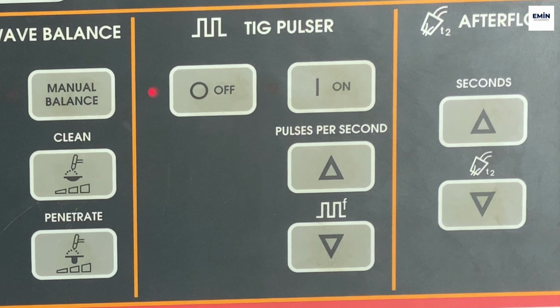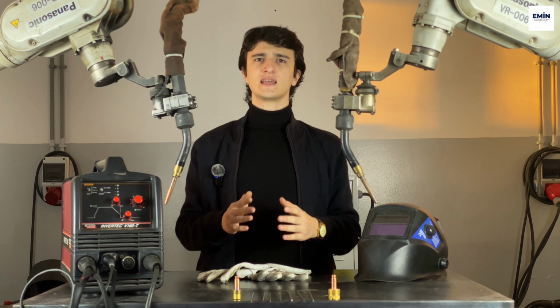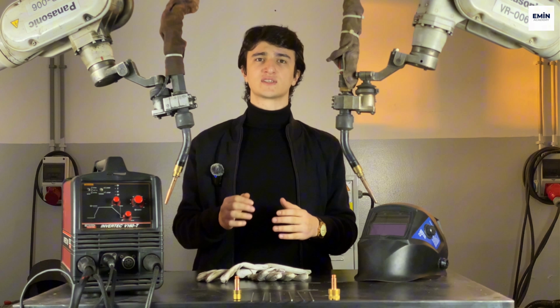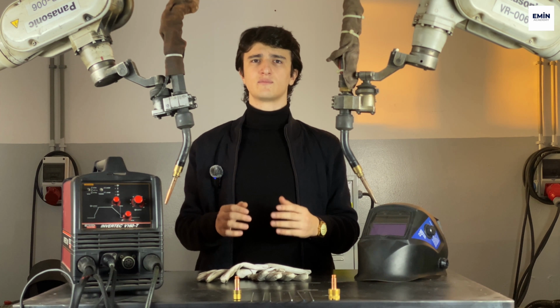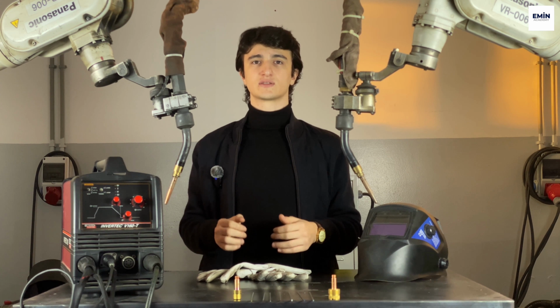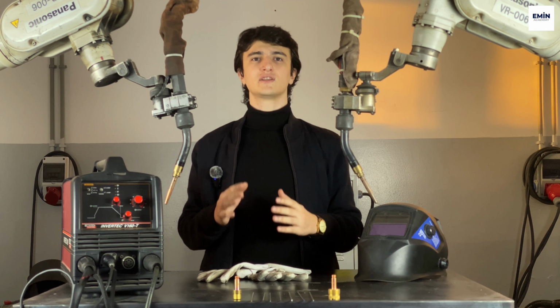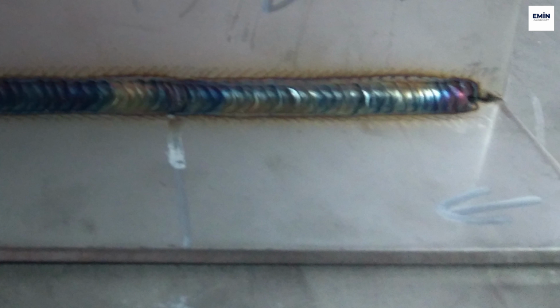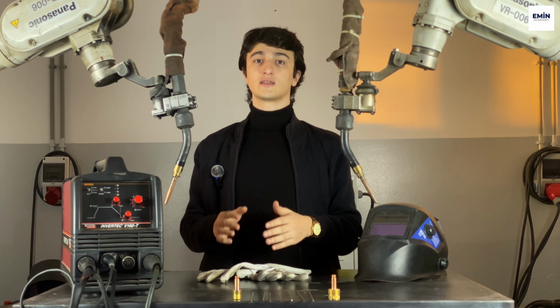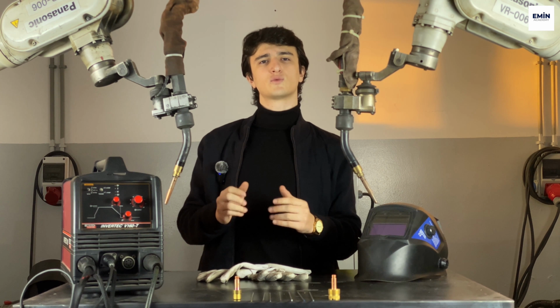Additionally, using pulsed current is very effective for keeping the heat input under control. Thanks to pulsed current, heat buildup is reduced and the weld becomes narrower and more controlled. In thin materials, the risk of burn-through decreases and distortion is minimized. When there is excessive heat, blue-purple discoloration and distortion occur. This means that the corrosion resistance has decreased. Remember, a weld that looks good but is overheated is a weak weld.